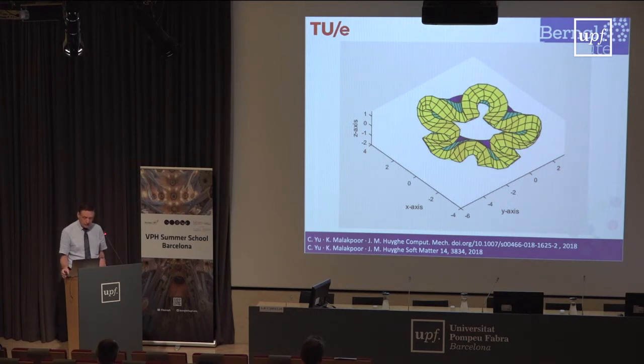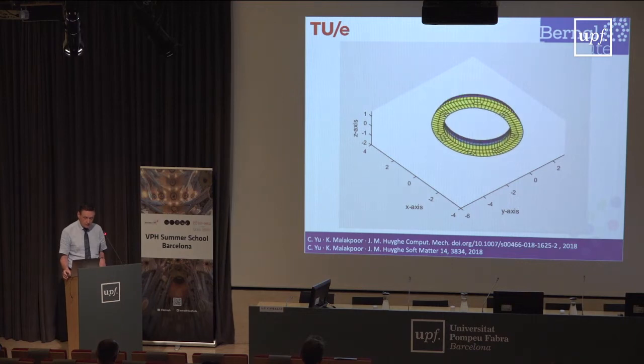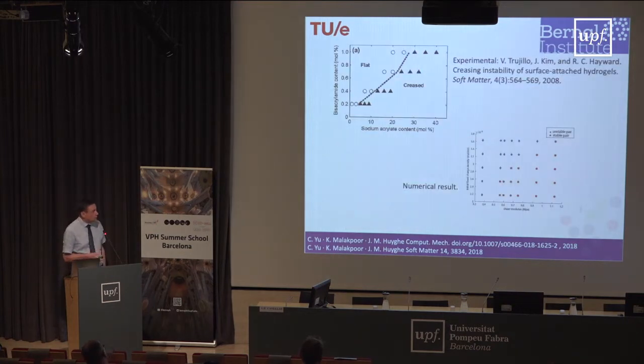And this kind of analysis is the one which is happening. And you can actually verify also experimentally that the phenomena that you calculate correspond to what you measure. You can plot one relative to the other, the swelling propensity and the stiffness, and then you get one side of the curve where there is surface instability and the other side where there is no surface instability. And same thing with numerical result, stiffness versus swelling, and one side is unstable and the other one is not.